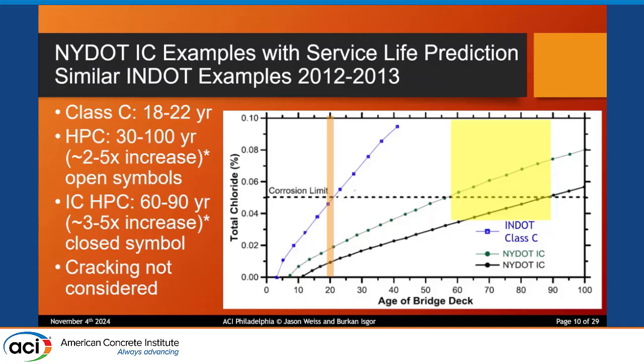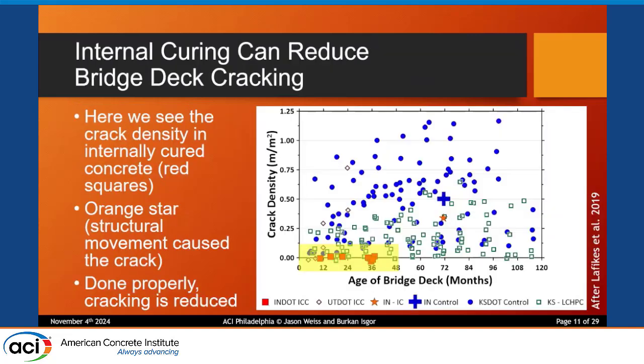So again, our overall goal was reducing cracks. By using this with some SCMs and getting additional hydration, we're also improving the resistance to chloride penetration. Right? And just to show that it's not just one lab test, these are surveys. This was a survey done using Kansas's data and looking at some of the bridge decks that were done in Indiana with internal curing. What you notice is here are where the bridge decks were that are internally cured. Here's where the typical bridge decks are in terms of crack density. I see a trend. I don't know if anybody else does. Substantial reduction in cracking. So I'm always amazed when we do another survey and we find out that cracks are a big concern for DOTs. There might be a solution here to reduce cracking in bridge decks.